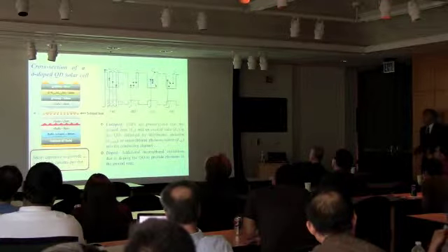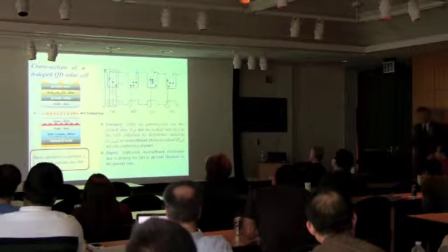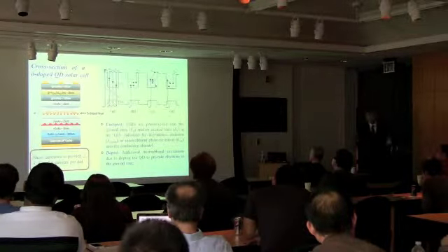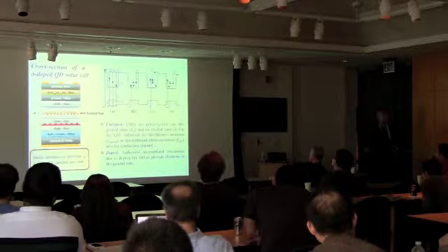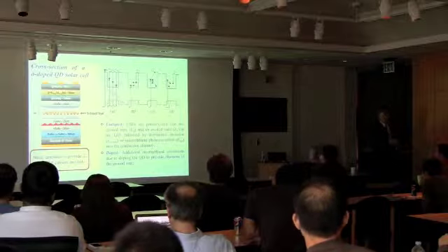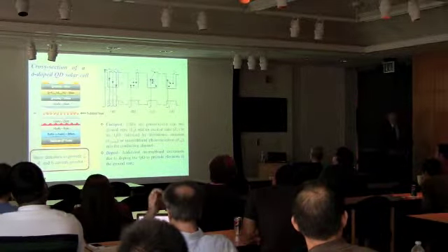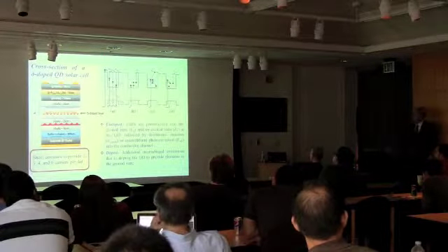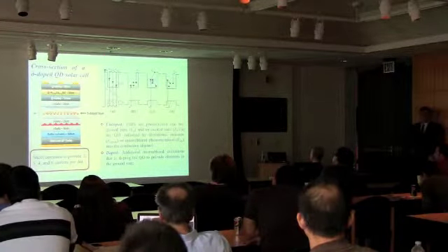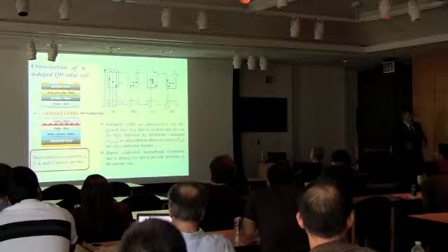And what we do is again the same story, that we dope. Now, in the previous example, it was obvious for you, yeah? You have photodetectors that are working on electrons, so the doping was obvious. You need to dope this material with such a dopant that charges the dots negative. But now you have two types of carriers in this material. You have holes and you have electrons. And now what? If you are doping with donors, you create more electrons, but it will be attractive for the holes, yeah? And vice versa.